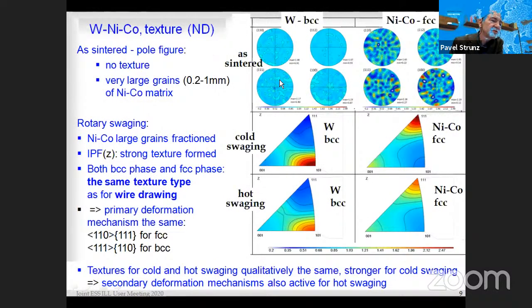You can see from the pole figures that there is no texture at the beginning in both phases, but in the second phase, these large spots show us that there are large grains, even from the point of view of neutron diffraction. Rotary swaging fractioned these large grains, and also these inverse pole figures show us that they built a quite large deformation texture in both phases. And this type of texture is the same as for wire drawing. That means that highly probably the deformation mechanism is the same as for wire drawing.